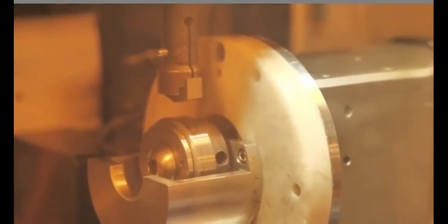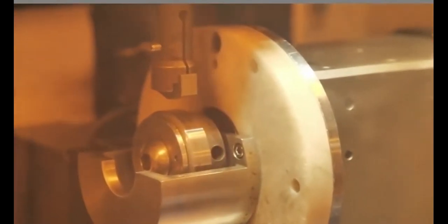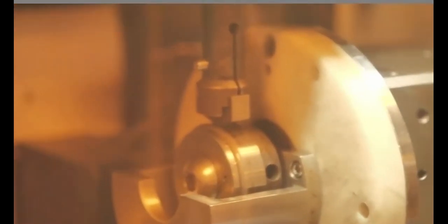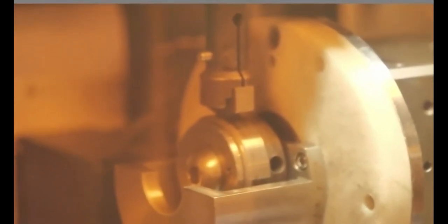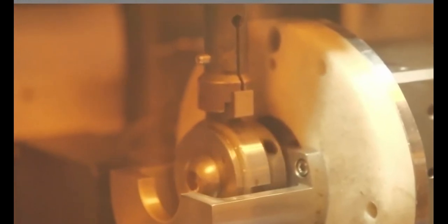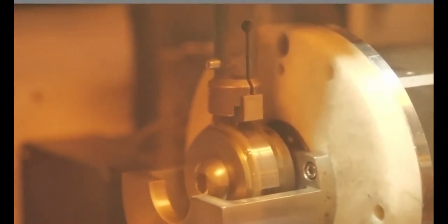So it's recreating that rolling, that line contact between the raceway and the roller. We have this oil bath, so we can put some lubricants in there. That way we can investigate the effect of the lubrication in between that contact.